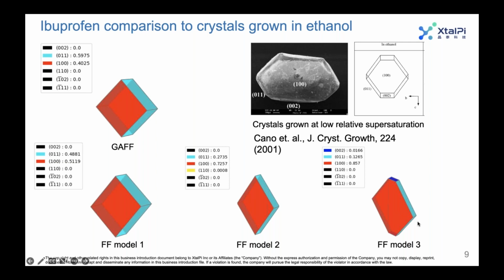It's only with force field model 3, where you're taking into account both the crystal interaction energies and the solution interaction energies, that we get something that's qualitatively very similar to the morphology that's actually obtained. We get this 002 face, and we also get a very thin plate-like structure.